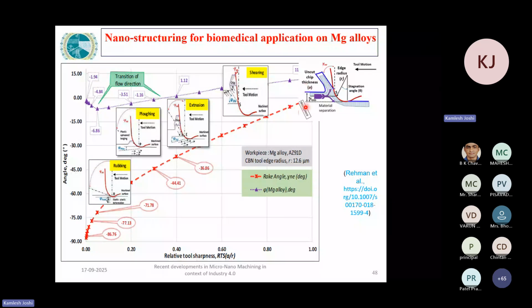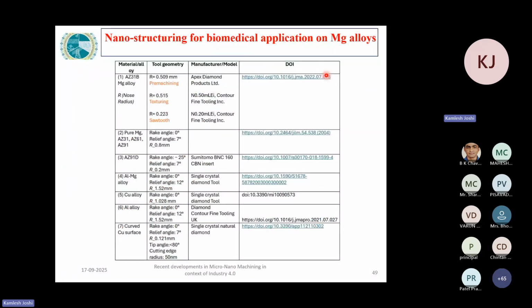So in order to get the desired uncut chip thickness level and maintain the relative tool sharpness ratio, we have to select the tool edge radius based on the calculation as shown by Professor Rahman and his team in this diagram. So we have done some literature review and found that for machining of AZ31B magnesium alloy, people have used a tool radius of 0.9 micrometer for pre-machining, 0.5 for texturing, and 0.2 for sawtooth type of profile formation. These are the manufacturers of the tool.